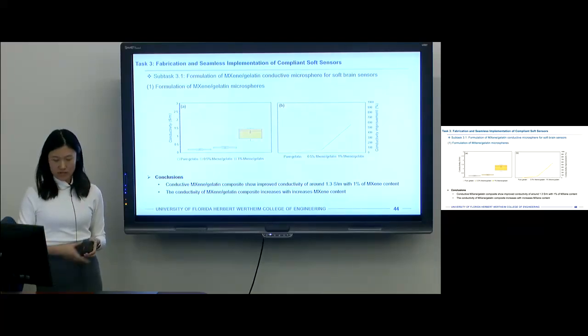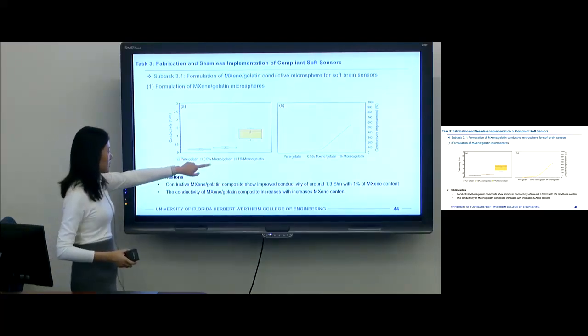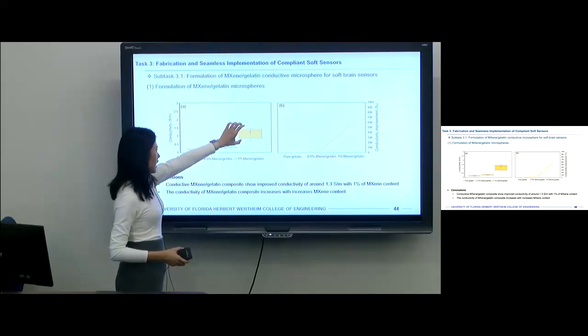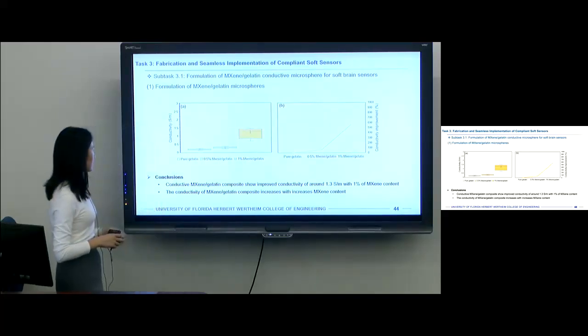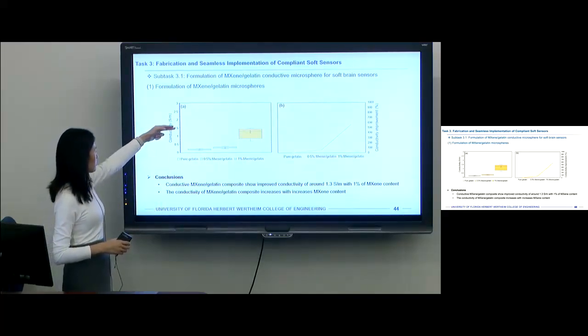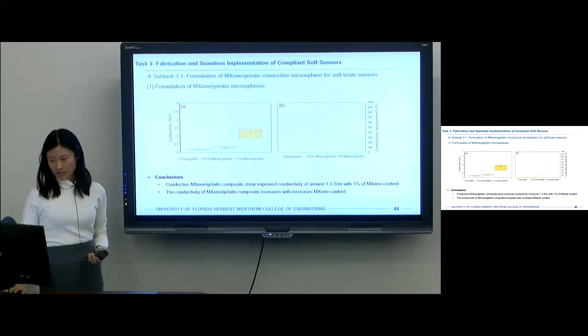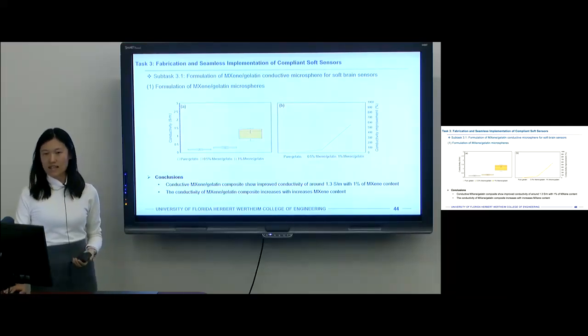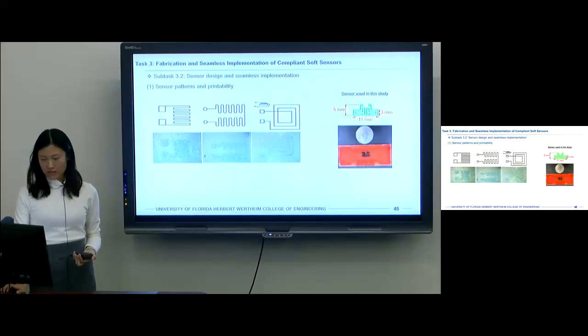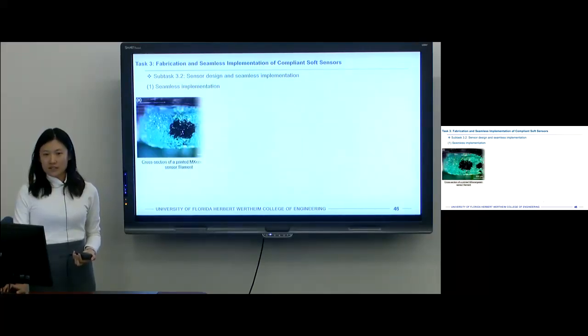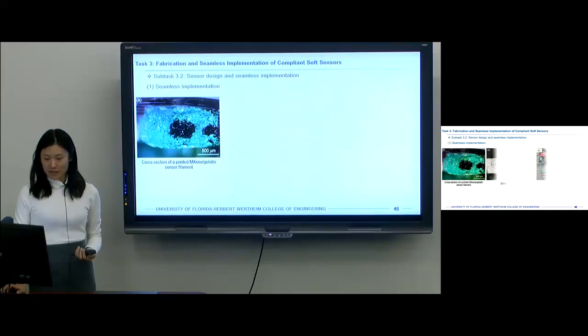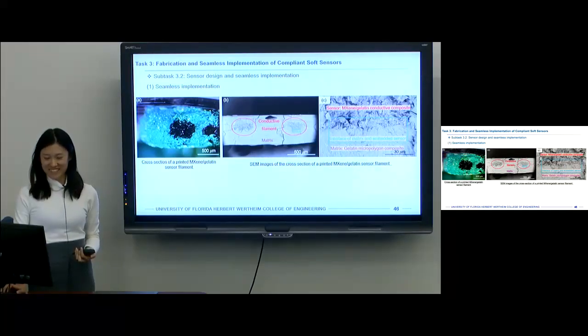Here are some measurements. Compared with pure gelatin, the MXene gelatin has huge improvements regarding conductivity, around 600% improvement. And we have sensors printed inside of the gelatin. Time is almost up, so I'm going to hurry up here.